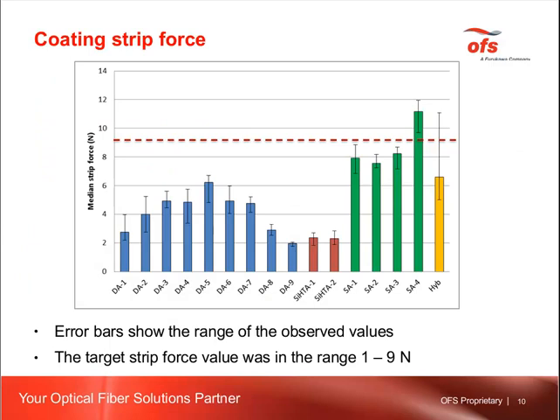So we drew these fibers and we tested them using an extensive test program. The first half of the test was so-called common tests. So they are relevant, for instance, to telecom fibers. And the first test in this series is the coating strip force. If you have a fiber with an acrylate coating, then ideally you should be able to strip this coating mechanically without breaking the rest of the fiber.